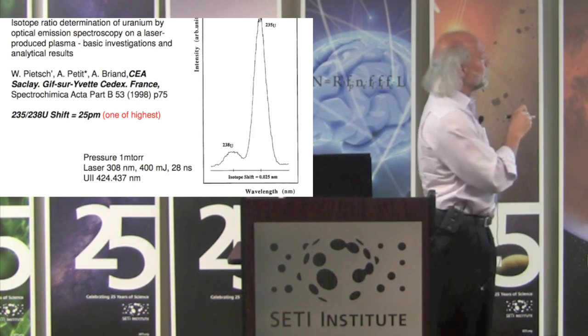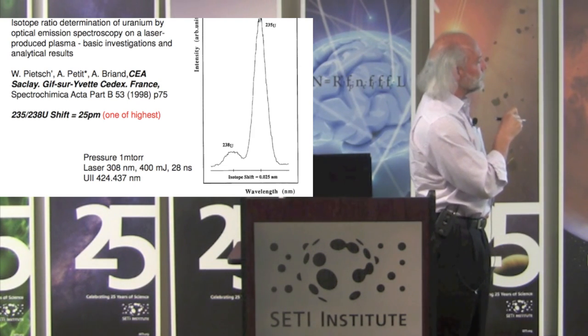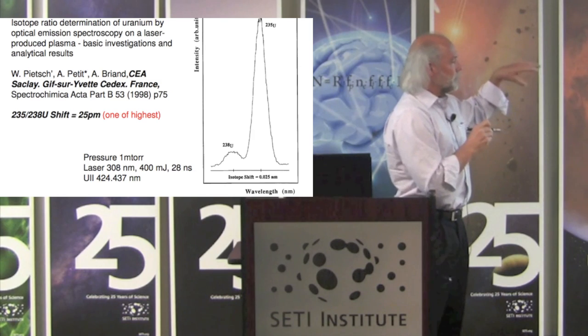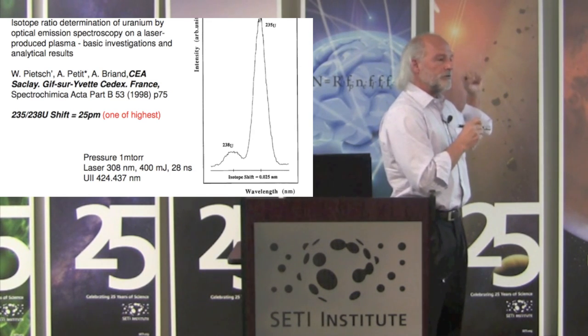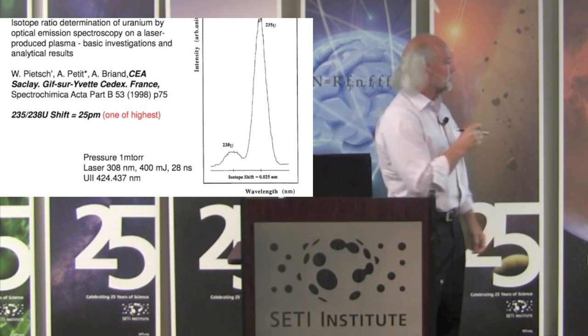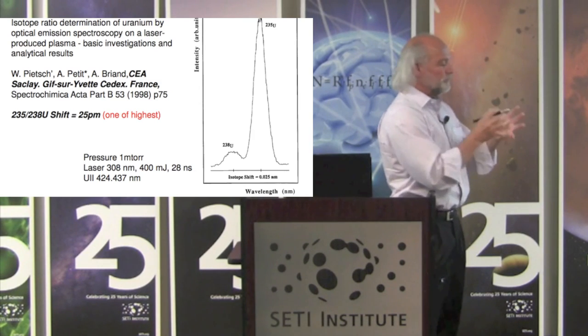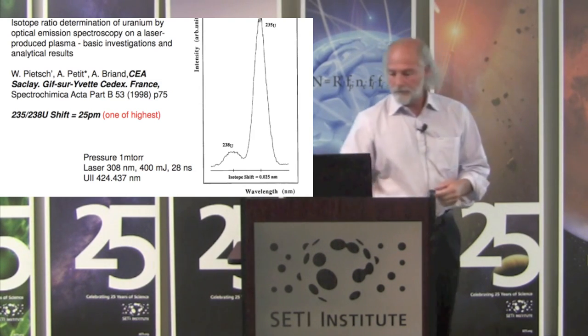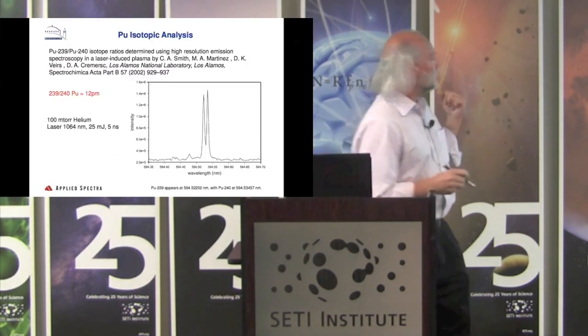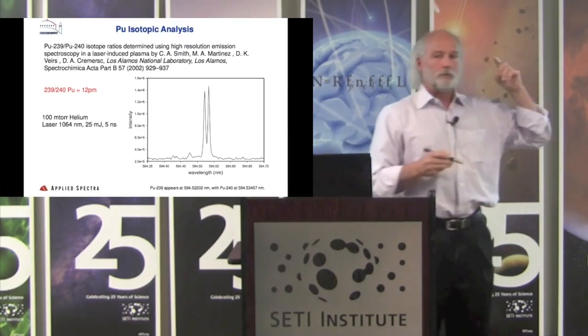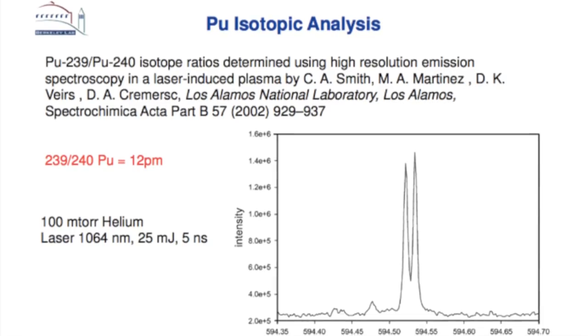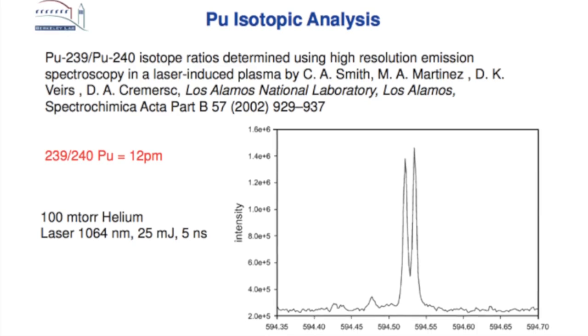This is actually from France, but very similar to what the Los Alamos group did. So this is some of the first work where people did show you could do isotope analysis in a LIBS plasma, but it had to be in a special chamber with reduced pressure. This is the Los Alamos work. Now remember, uranium has a 25 picometer shift. Plutonium only has about a 12 picometer shift.